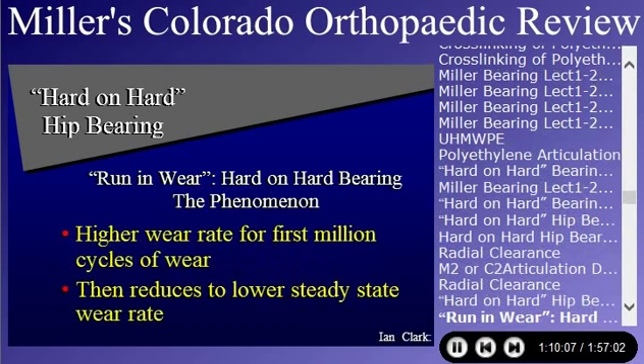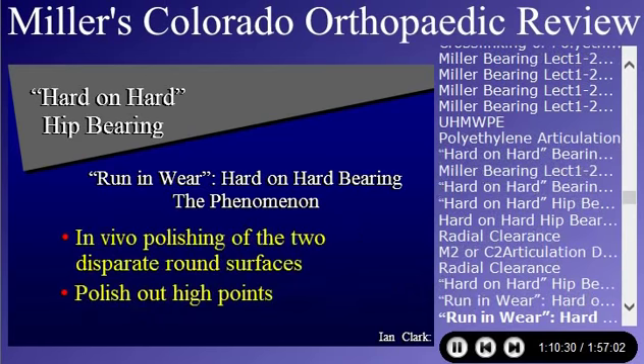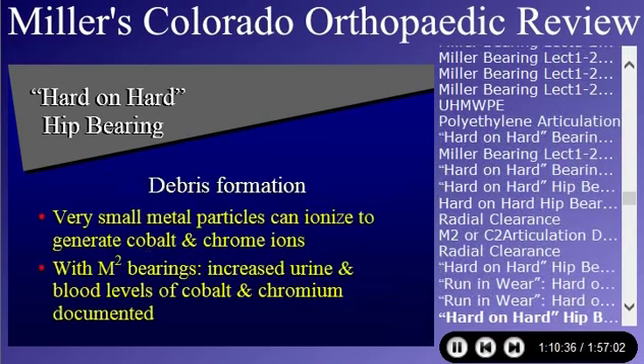There's also a phenomenon of what we call run-in wear. When you put these metal bearings in, it's just like a brand new car's first 10,000 miles, or the hip, the first million cycles, you're going to get excessive wear until you rub those high points out. That is run-in wear. So you have a high wear rate for the first million cycles, and then you reduce to a low steady state thereafter. And that's the definition of run-in wear with hard-on-hard bearing. It represents an in vivo polishing of the two round surfaces. You polish out basically the high points, and that's all you need to know about that.